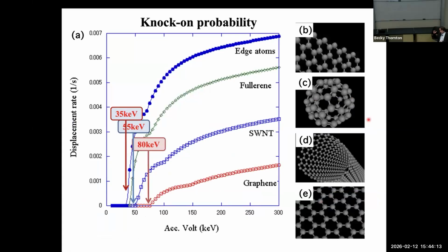Okay, so how low should we go? This is quite a simple calculation of the knock-on probability. If you want to see graphene, you have to go below 80 keV. This is the knock-on displacement probability. If you have nanotubes or fullerene, you have to go a little bit lower. And if you really want to get some atomic information from the edge of carbon or graphene atoms, you have to go below 35. So this is our goal.